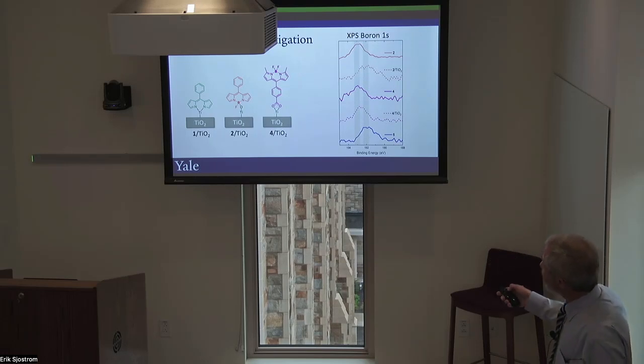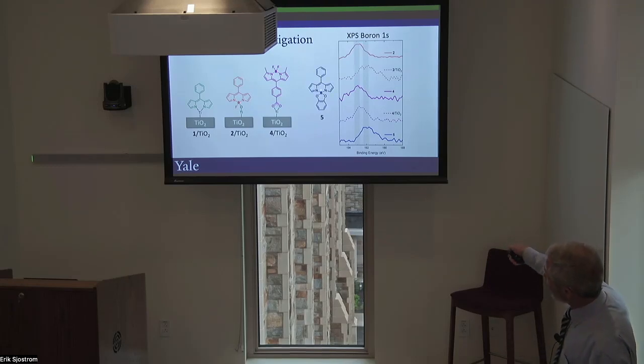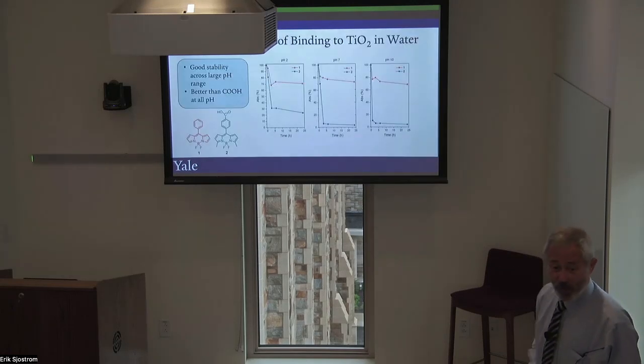To probe this a little further, what we suspected was that the boron was binding through an oxygen to the titanium to form a boron-oxygen-titanium bond. So we synthesized this model complex with oxygen coordination to boron. And interestingly, the model complex has an energy very similar to the energy of the Brudvig bound to titanium oxide. So we're pretty sure that the boron is bound through this oxygen linkage like this. And it's incredibly stably bound.